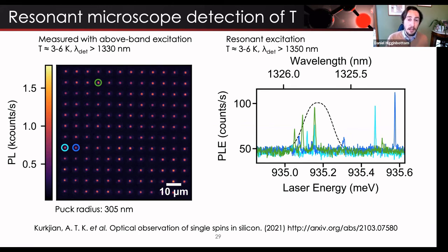So we're assuming that every center that we're looking at is optimally positioned, is optimally coupled to a puck which performs the best we could possibly simulate. And we're only subtracting the losses which we were able to measure and quantify. There are known losses which we haven't quantified, which also exist. And if you make our best guess estimates for what those known unknowns are, then we get closer to a 10% quantum efficiency.